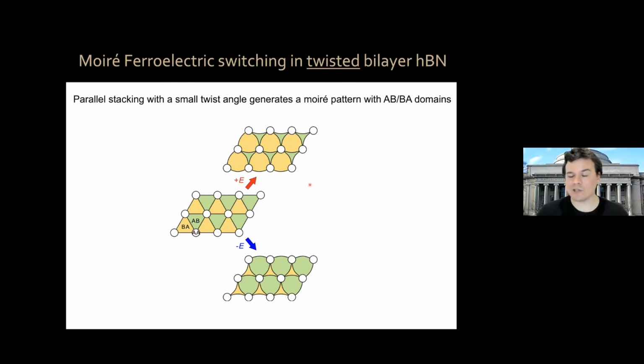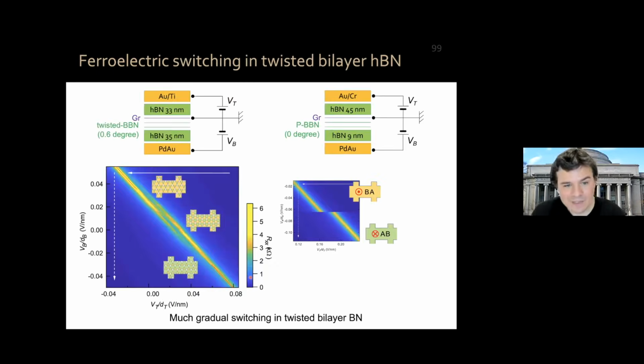We can actually also make a small twist angle. And in that case, we have a Moiré pattern of AB and BA domains, which now with an electric field, we can increase the size of one domain or increase the size of the other domain, okay? And indeed, if we fabricate devices, this is now twisted bilayer boron nitride with a 0.6 degree rotation angle. Again, this is something we do on purpose.